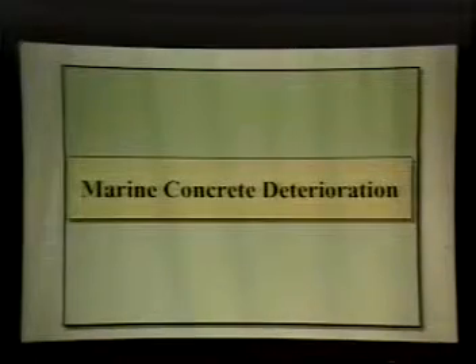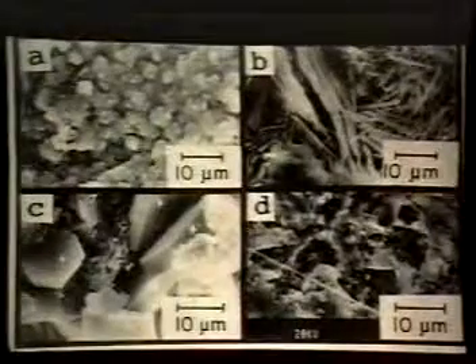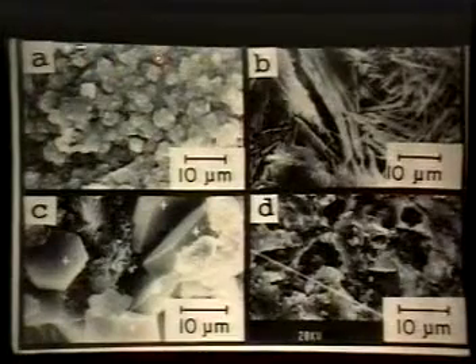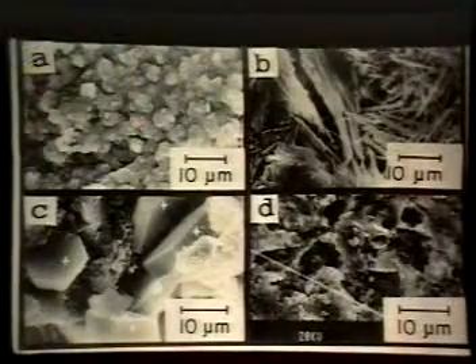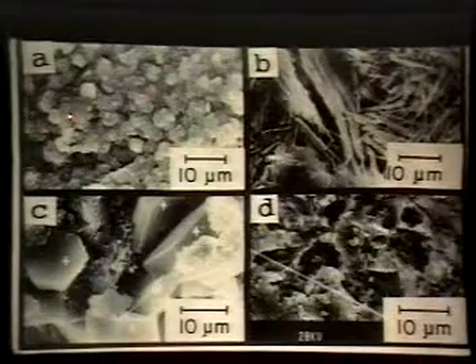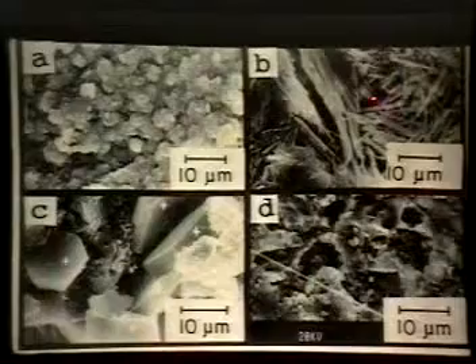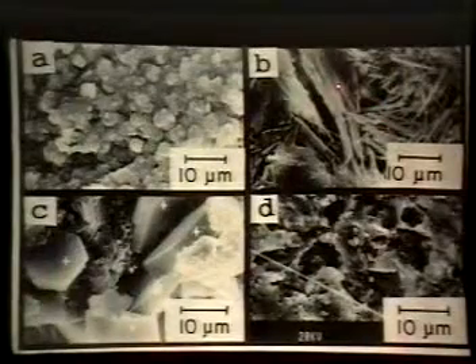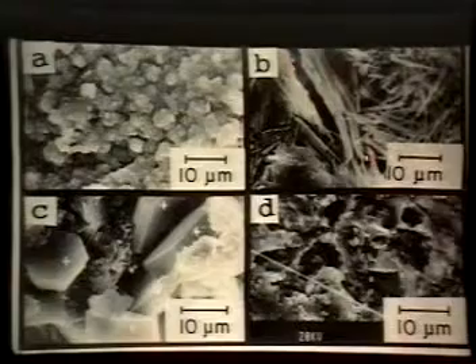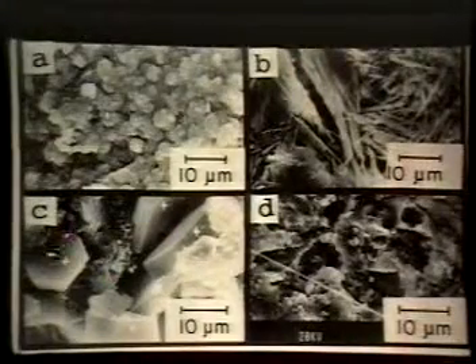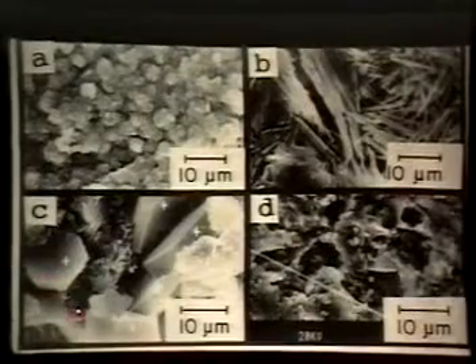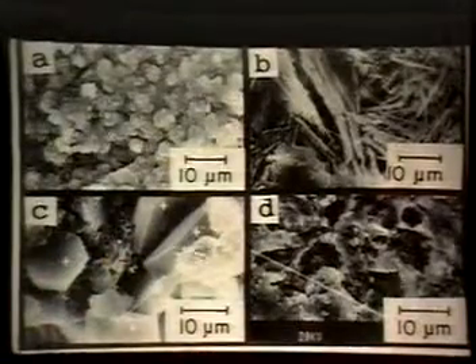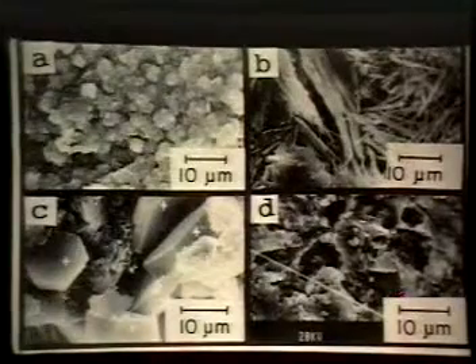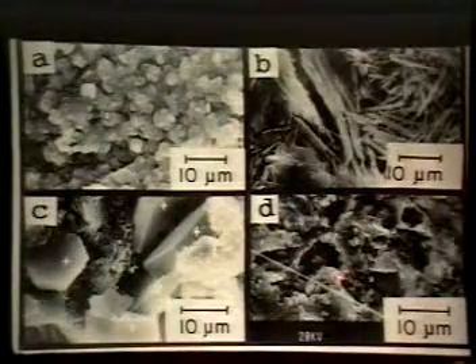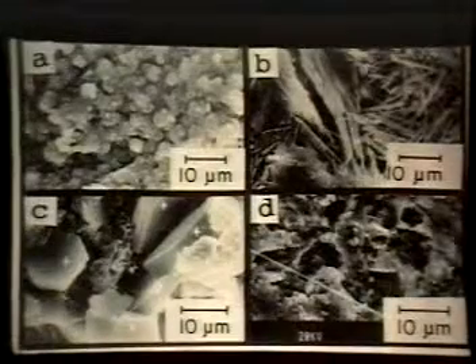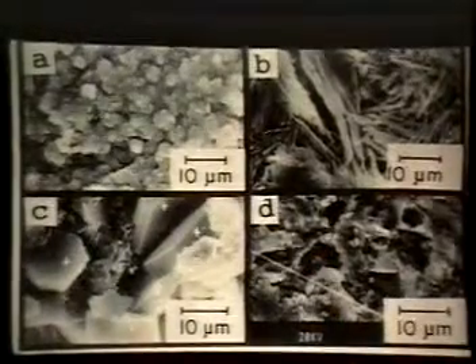Marine concrete deterioration is another subject which is of importance to Houston. This is what you call a combination of brucite and calcite, magnesium hydroxide from salt water. Sometimes it can act as a protective membrane, a natural protective membrane on the concrete. This is sulfate attack of marine concrete, forming ettringite crystals. As you can see, this is where the expansion occurs. You have chloroaluminate crystals. We are still not sure whether it has a pore blocking effect or an adverse effect. And this is what you see, increased porosity on the surface of the concrete, leaching of constituents. Lime, which is readily dissolvable, leaches out, and the fine aggregates have leached out.